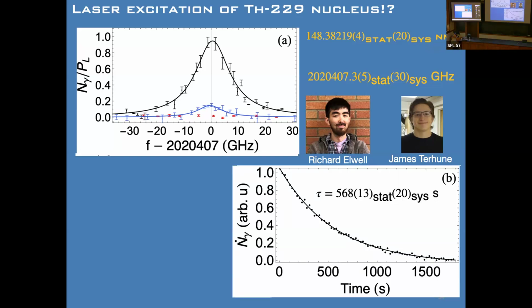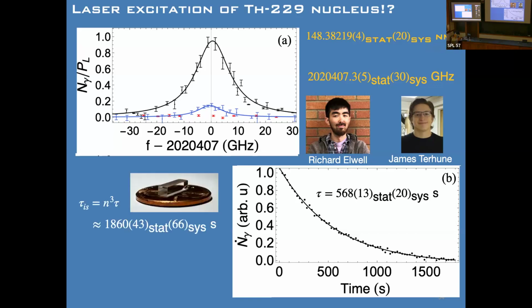We can measure the lifetime, and it's sort of exactly what we expected. One thing I'll point out, because it's kind of a fun physics problem. It's a great comp problem if you guys still get comps. This is a magnetic dipole transition. So if you put it in a dielectric, the lifetime gets shortened by n cubed because the density of photon states grows as n cubed, right? So the index of refraction, yeah. If it was an E1 transition, it just goes as n because the electric field would be screened by 1 over n, and then you square it. And so for magnetic dipoles, you get an n cubed.